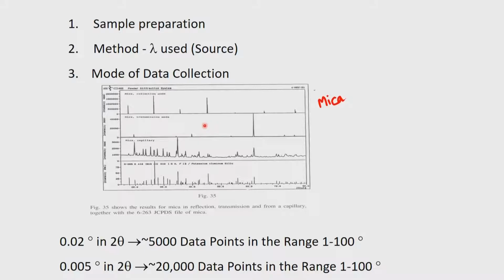This kind of thing happens in many layered compounds. There are a lot of people who work on layered inorganic materials, organic-inorganic layers, parallelly packed, the hybrid structures. In all those situations, these two methods are not the recommended methods for data collection. The recommended method is the Debye-Scherrer approach, the capillary method, where you rotate the sample.